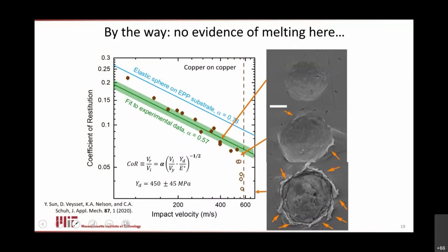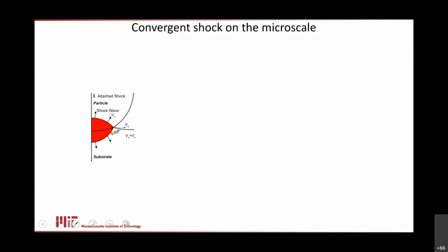And additionally, if you look at these jet lips here, there is no evidence here that any melting occurred. This doesn't look like a molten and resolidified structure at all. This looks like a plasticity phenomenon. It looks like tearing and extrusion and shearing, right? So we think this is a solid state ejecta projection, solid state splash. In fact, we are of the opinion that what you're seeing here are hydrodynamic jetting events.